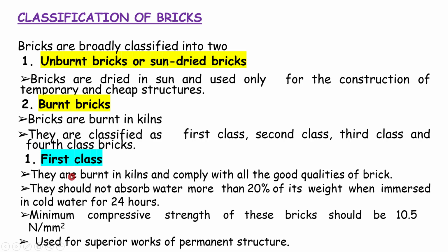The first class bricks are burnt in kilns and comply with all the good qualities of the brick. So this is one of the superior quality bricks. What are the superior qualities required by a brick? They should not absorb more than 20% of their weight when immersed in cold water for 24 hours. Suppose, let's assume that a brick has a weight of 1 kg, 1000 gram.